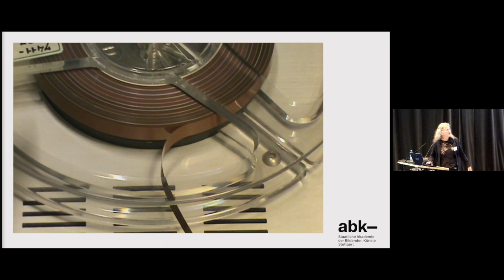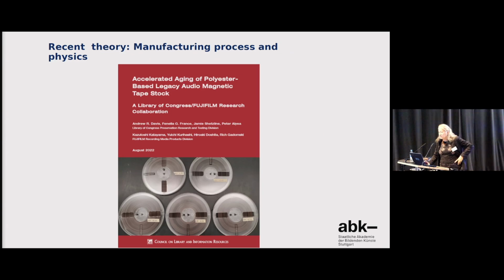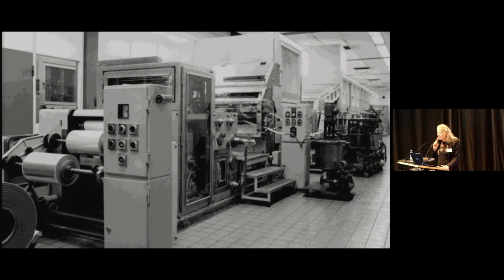And if the video was playing, I could show you that this is a non-back coated acetate tape, non-back coated, which is sticky, definitely sticky. This leads us to the third and last theory, the manufacturing process and the physics. A recent study from the Library of Congress, Andrew Davis and Fenella Franz and the colleagues, wanted to artificially age samples, and they found out that they cannot, in the laboratory, provoke the chain scission. They cannot provoke binder breakdown. It's not possible. They aged it for a year under whatever conditions, and the tape became not sticky. Why? Because the production process has such a high influence.